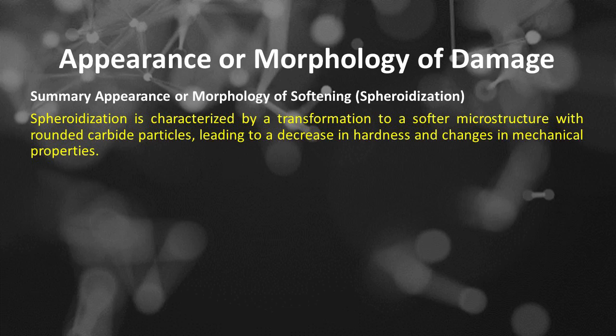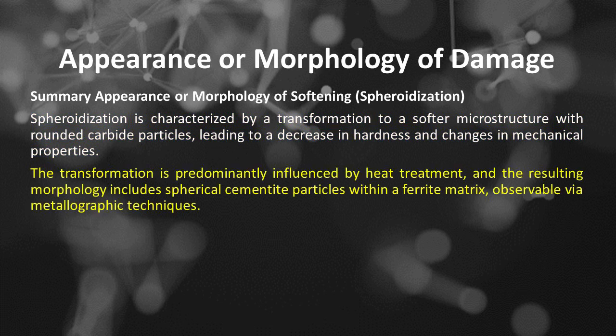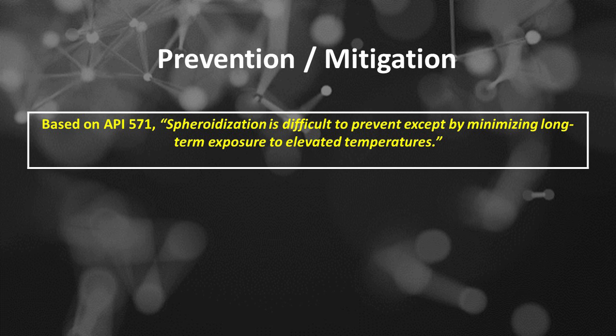Spheroidization is characterized by a transformation to a softer microstructure with rounded carbide particles, leading to a decrease in hardness and changes in mechanical properties. The transformation is predominantly influenced by heat treatment, and the resulting morphology includes spherical cementite particles within a ferrite matrix, observable via metallographic techniques. Softening or spheroidization prevention or mitigation. Based on API 571, spheroidization is difficult to prevent except by minimizing long-term exposure to elevated temperatures.